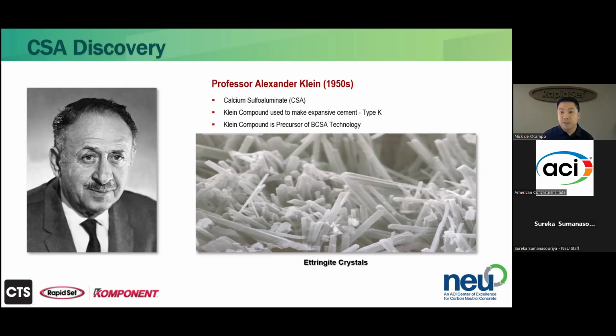CSA cement forms its ettringite very early. So these needle-like structures here on the slide form in the very beginning of hydration, prior to the development of any calcium silicate hydrate from belite or from other hydration products. So rather than being a destructive force, ettringite is actually in a synergistic relationship with the other hydration products in the cement. The needle-like crystals that form in the beginning serve as nucleation sites, or as the backbone around which CSH and other products from hydration form.